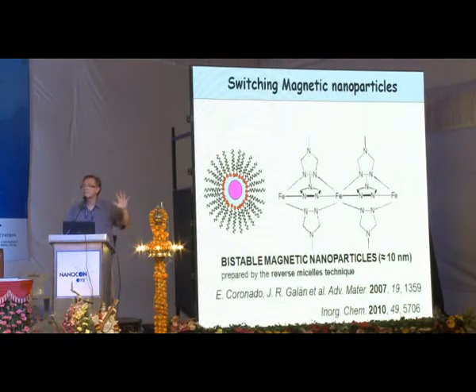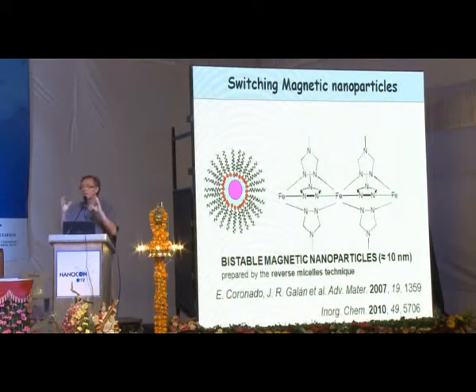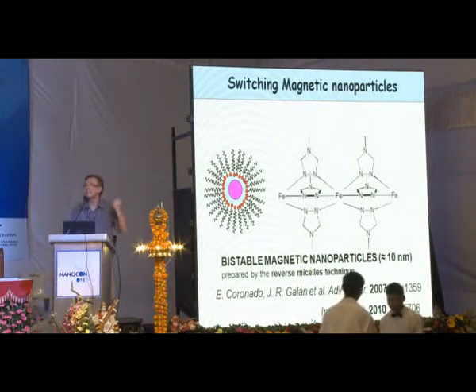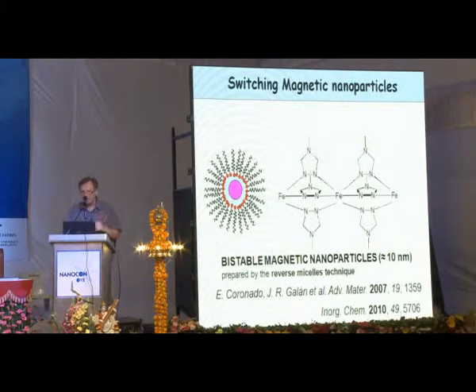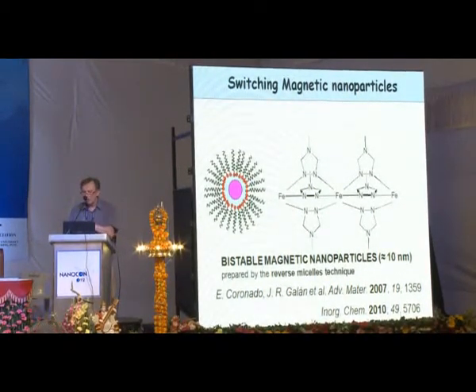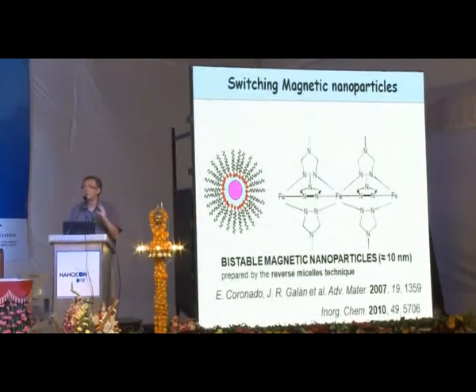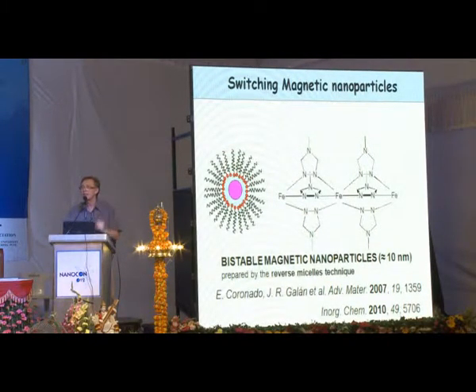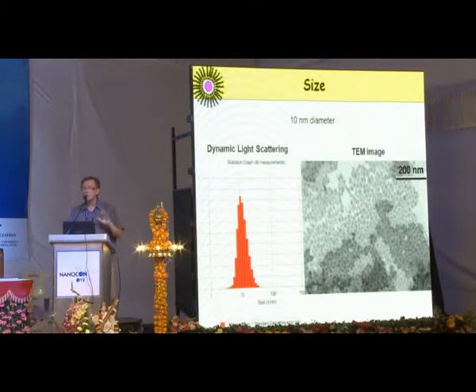This system has been studied in bulk for a long time. Our idea was: can we make devices in which we can tune the spin with temperature, light, or pressure, but at the nanoscale? Can we make nanoparticles that still exhibit this behavior? The answer is yes. We worked with a polymer of iron(II) with triazole ligands and produced nanoparticles of 5 to 10 nanometers by varying experimental conditions using the inverse micelle technique.